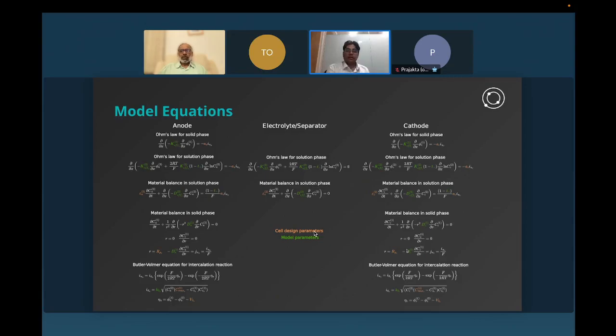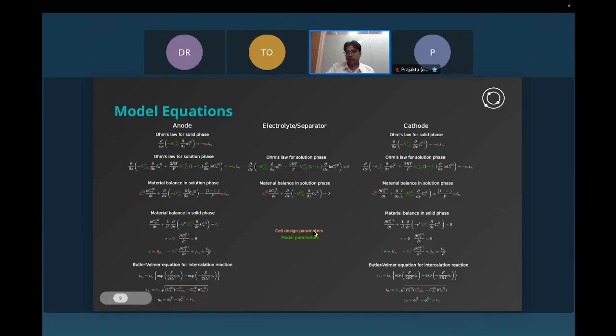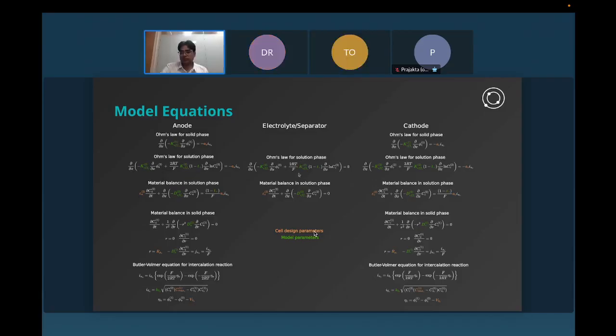Now, the processes that Dr. Raghu described in a mathematical form can be represented by the set of equations that you see on the screen. There are diffusion processes that we talked about, so those are the diffusion equations here for the electrolyte, and then the diffusions in the electrodes over here, and then you have also the potential which drives the migrations of the ions from one place to another. Similarly, the same kind of thing happens on the anode and cathode, undergoing similar kinds of processes. And then you have the diffusion and migration happening through the electrolyte, which is sitting in the separator.